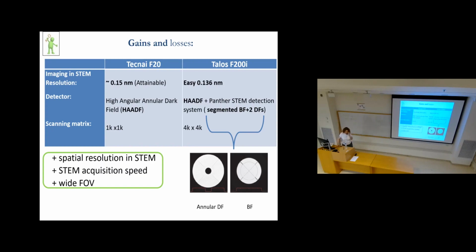Okay, so that practically means that for gold, for example, we didn't have enough resolution to get the lattice image in STEM on gold. What we succeeded to do, the lattice image in STEM on semiconductors. So the larger is the lattice parameter, the better. With our new Talos F200i, we have easy 1.36 angstrom. That means this kind of image.